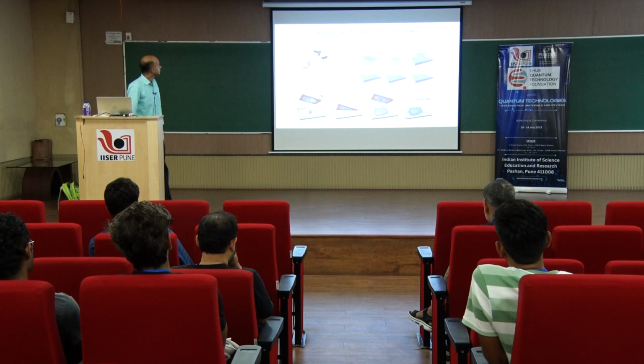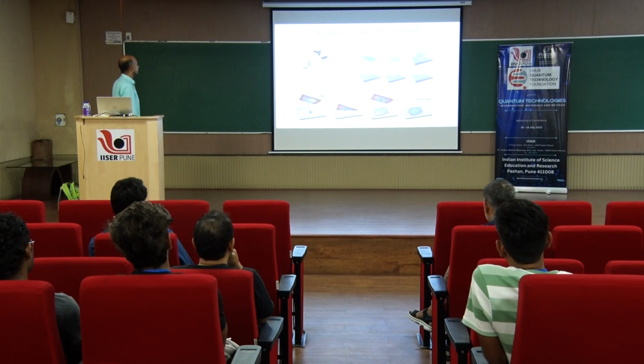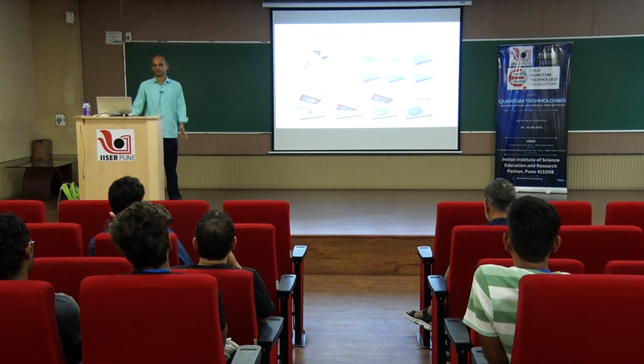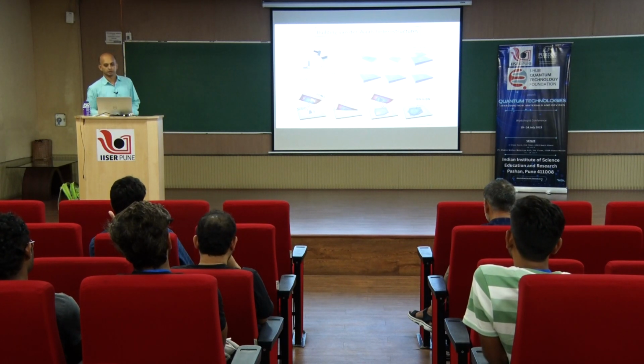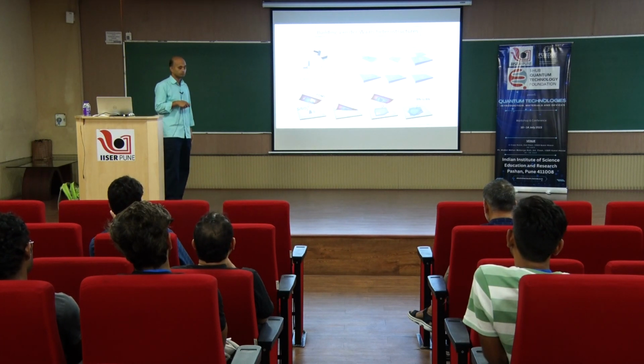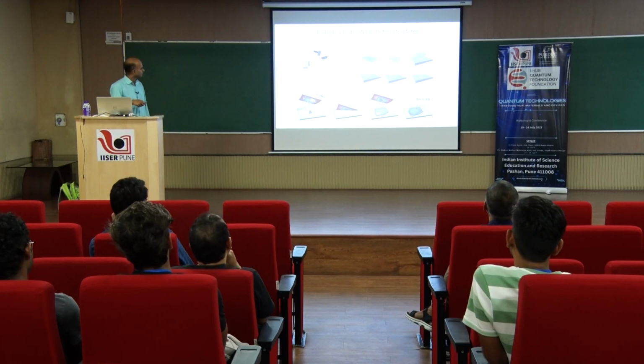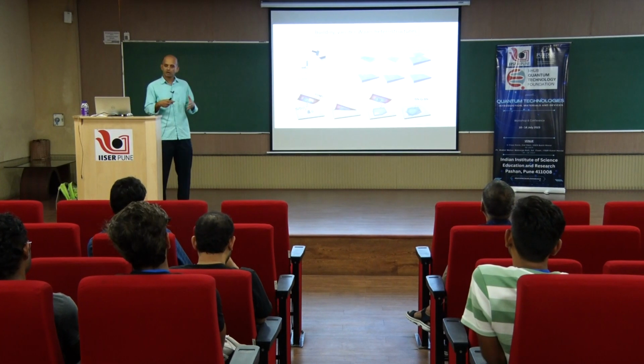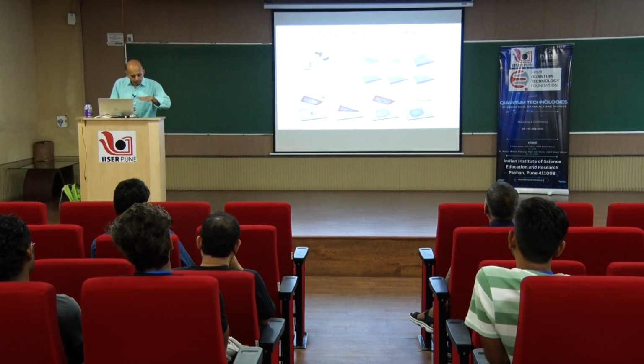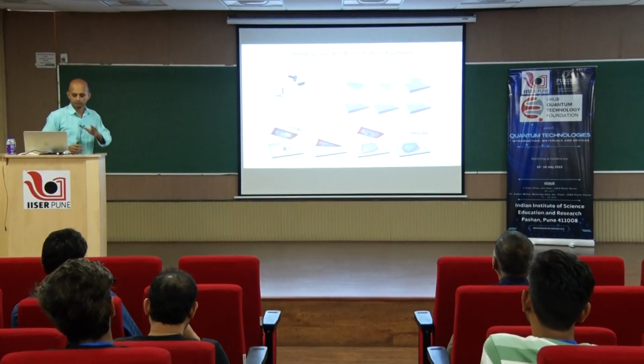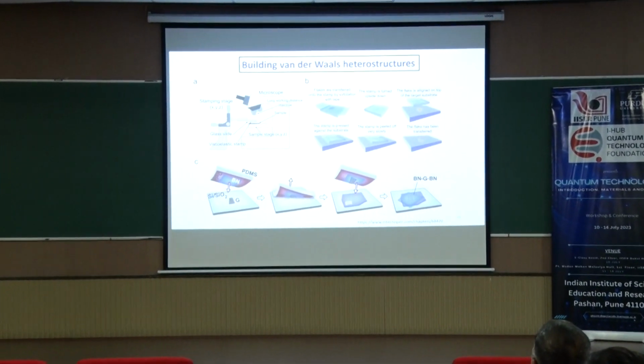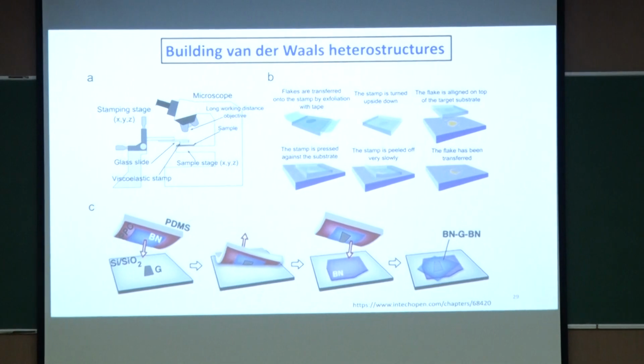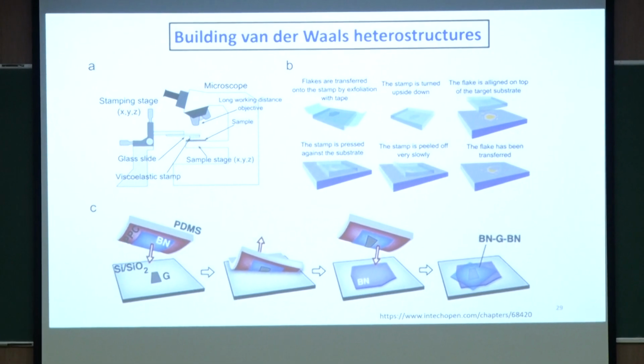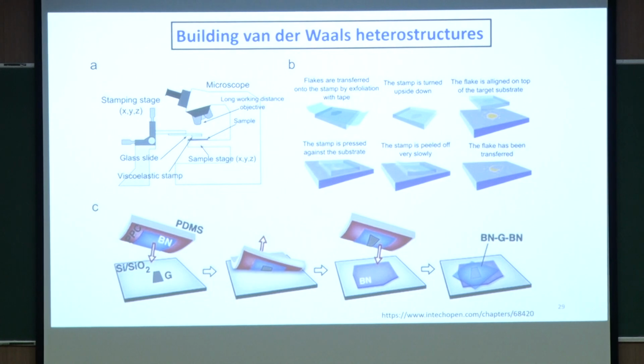Now, how do people do this? This is what people call a transfer stage. You put it under a microscope with a long working distance objective, and you use some PDMS or other material to exfoliate your monolayer, and then align them and press it. If you release it slowly, the property of PDMS is that it is a viscoelastic material. So, if you release it slowly, then it will release the monolayer. If you do it fast, then it will not release. Rather, if you want to pick it up, then you have to do it fast. But the same material, if you release it slowly, it will leave that material.